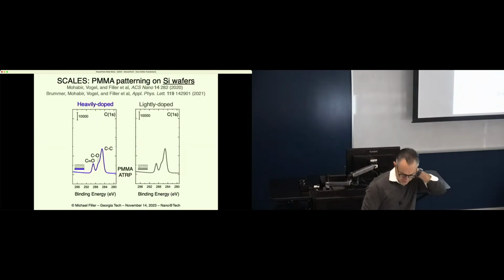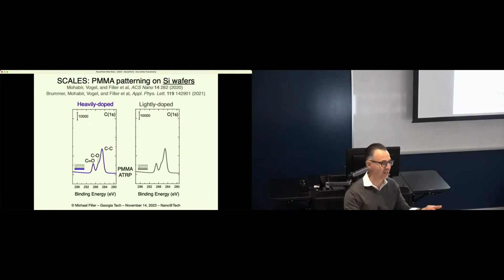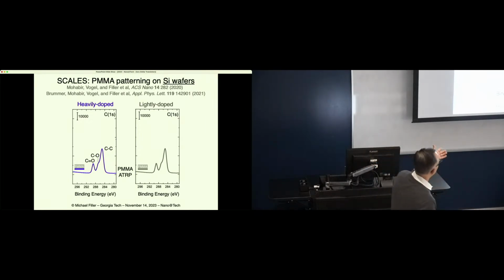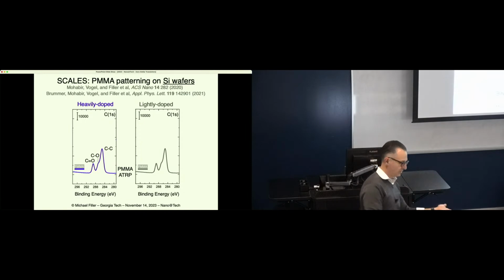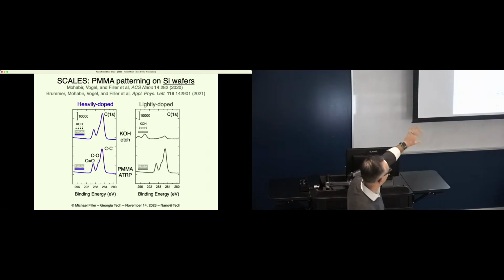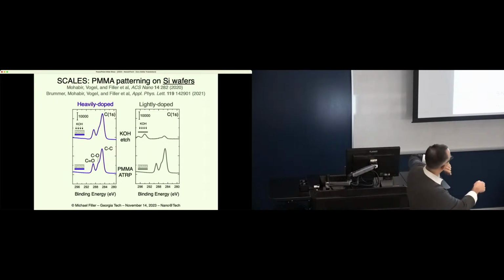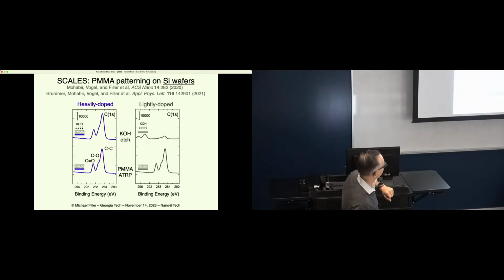And so here we started this process like a lot of our processes on wafers, because we have characterization techniques that allow us to look at this at the wafer scale that are really hard on the per nanowire scale. So this is on a wafer. This is a pattern wafer with some heavily doped regions and some lightly doped regions meant to represent the channel region and the source drain regions. And so here, after we do the polymerization, you can see the classic peaks of PMMA. And then we apply this selective etch technique. And sure enough, we're able to maintain the PMMA on the heavily doped regions, which is our goal, and pretty much remove it from the lightly doped regions. We see a little bit, by the way, the etchant is KOH based. We see a little bit of potassium here left over. But the basic concept works, at least on wafers.